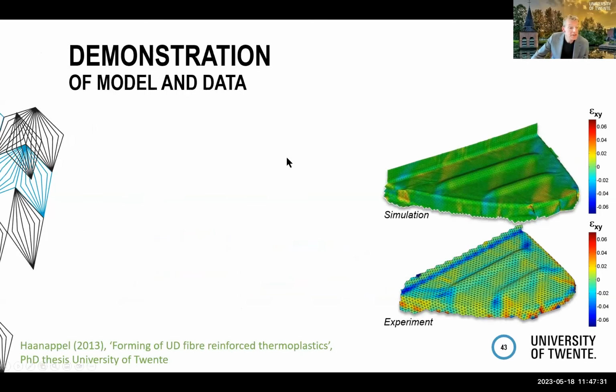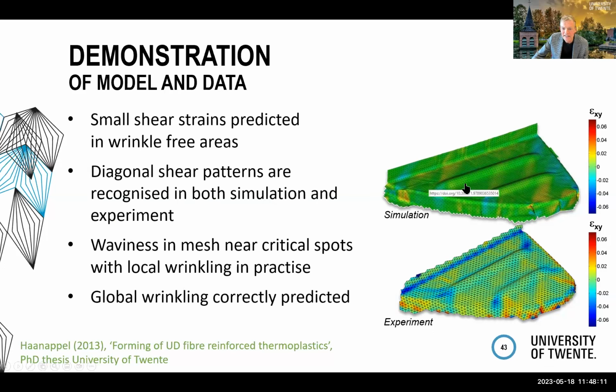Okay, concluding on all this modeling stuff, here we've got an example from 10 years ago, I see, where we compared DIC data. A grid was plotted on a laminate before forming, it was formed, and from that we could get the strain distribution, the shear strain in this case, and compared to the simulated results, we were reasonably pleased, I must say. The green areas, small shear strains, are predicted in the wrinkle-free areas. We can recognize some diagonal bluish patterns over here, which we also recognize in the experiment, where we predict waviness. We also saw local wrinkling in practice, and the global wrinkling is correctly predicted.